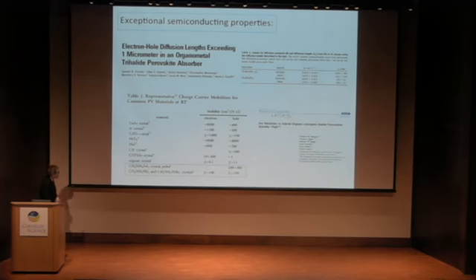You might think, okay, well, the fact they have a big diffusion length probably means they have high mobilities. And actually, it was pointed out in this paper, published fairly recently, that there's nothing terribly exceptional about their mobilities when you compare them to other more conventional materials. They're about right. And so that led them to suggest in this paper that there was something else behind all of this, that there was some coupling between electronic properties and also the phonons in these materials.